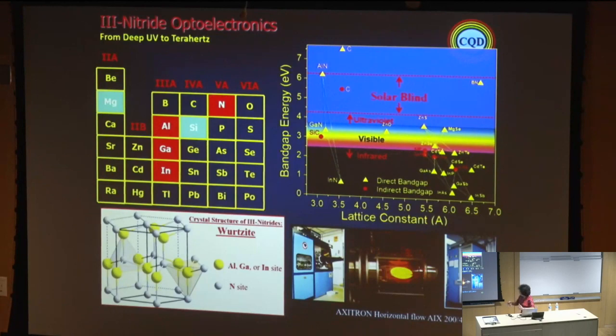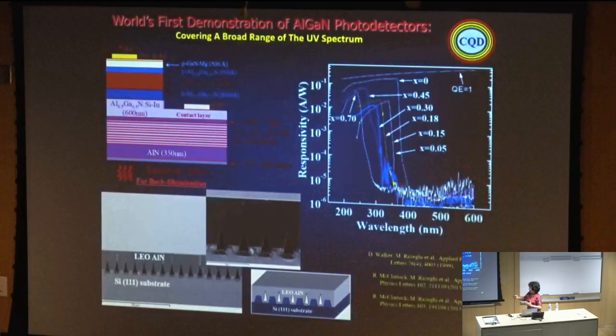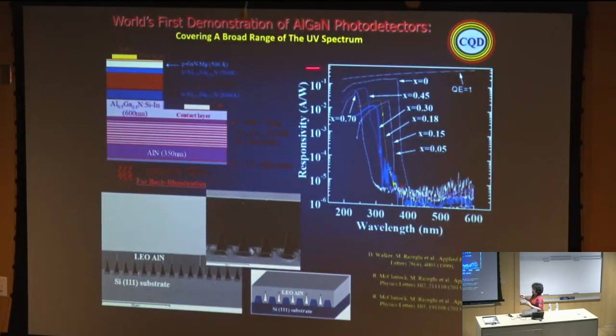But for that, the best substrate we use is sapphire, because sapphire is wurtzite, but has a big lattice mismatch. But we can manage the structure to put on sapphire. And here is the PIN. When we do the PIN structure, if you do the forward bias for the interband, you have emission, and by the reverse bias, you can have detection.